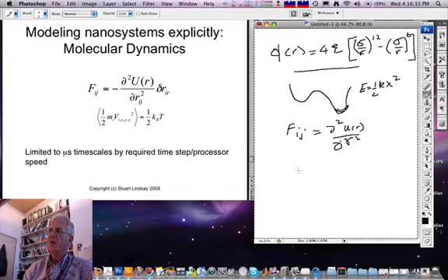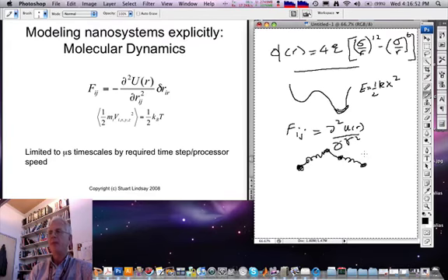So armed with force constants and particle masses, one can then set up some model of the system, set it into motion with random velocities given by the equipartition theorem as shown on this slide, and then see what happens to the system. The overall process is limited not just by the number of atoms, but by the time steps required to make the computation.